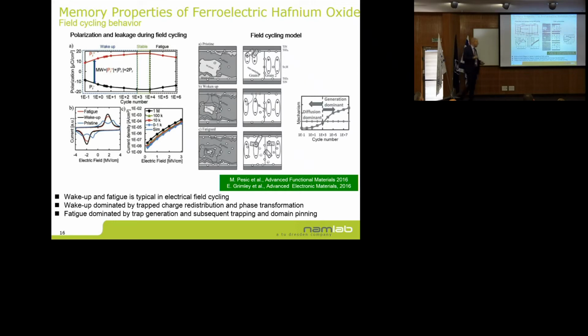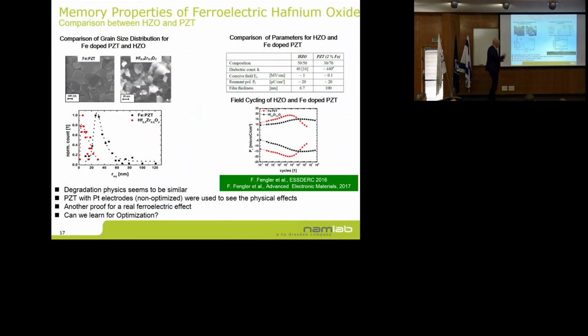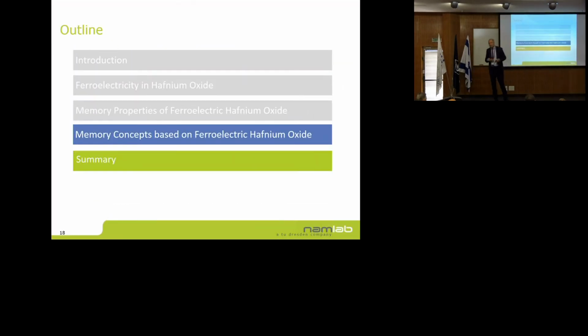And we did extensive modeling, trying to understand what's happening. And it seems like in the wake-up phase, mainly the existing defects, which could be oxygen vacancies, but it could also be something else, are redistributed in the film. And then during the fatigue, we are generating new defects in the film. Yeah? So this can also help us to extend the cycling lifetime. I want to skip this one. This is just a comparison with PZT, showing that it does not drastically behave differently.